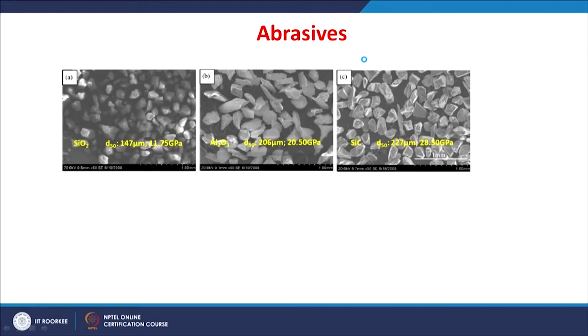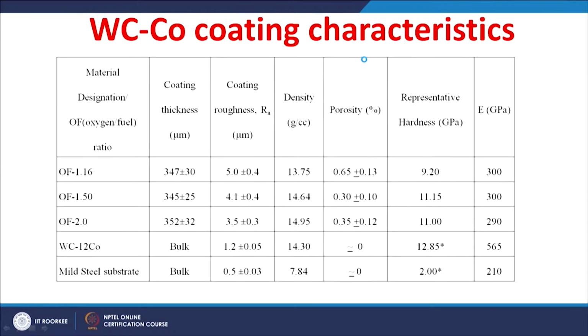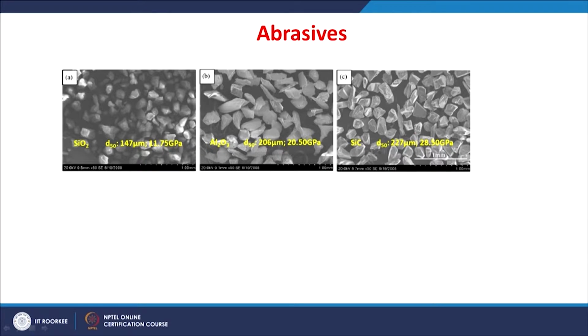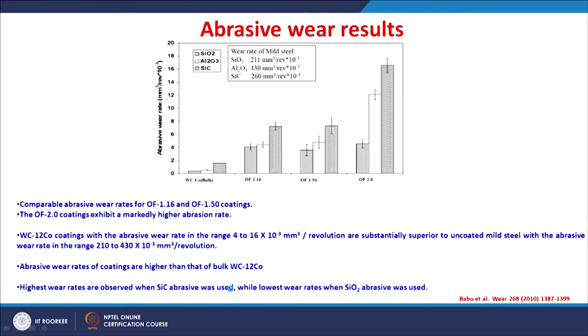In this study, the abrasives used were silicon oxide, aluminum oxide and silicon carbide. Silicon oxide of around 11.75 gigapascal hardness was selected, which is similar to the hardness of these coatings. And then an extremely hard abrasive, silicon carbide, was also used, with a hardness of around 28.5 gigapascal, and aluminum oxide particles having an intermediate hardness of 20.5 gigapascal were also used. You can see the size of the particles varied between 150 to 200 micrometer for the different abrasives. These abrasives were used to study the abrasion wear of the tungsten carbide cobalt coating.